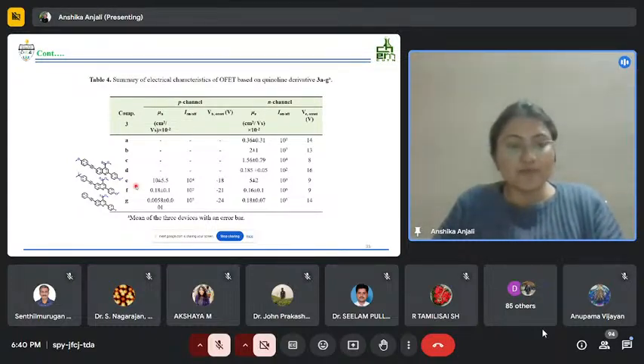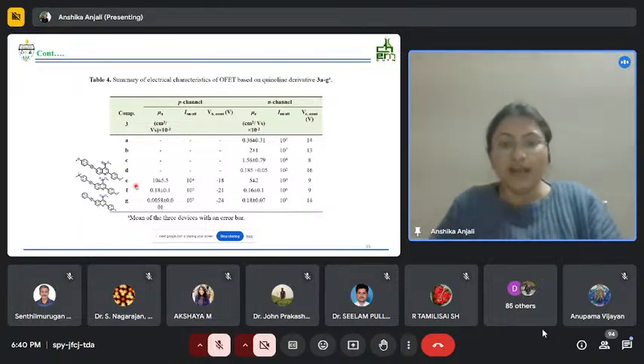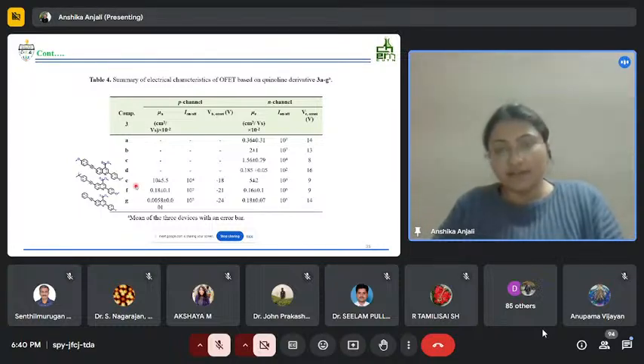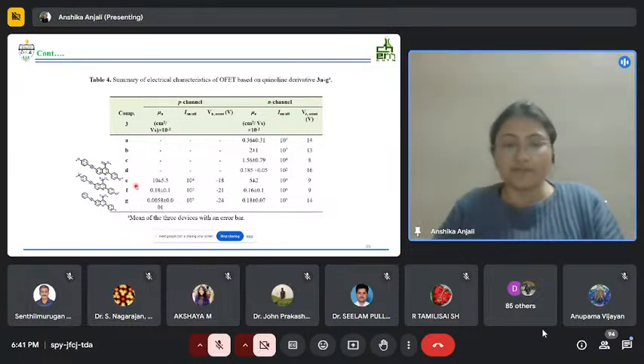The better results were observed for the 4-methoxyphenyl substituted compound 3E, where we have gotten a hole mobility of 0.1 centimeter square per volt per second, with a current on-off ratio of 10 raised to power 4 and a threshold voltage of minus 18. This compound also resulted in an electron mobility of 0.05 centimeter square per volt per second, with a current on-off ratio of 10 raised to power 3 and threshold voltage of 9.